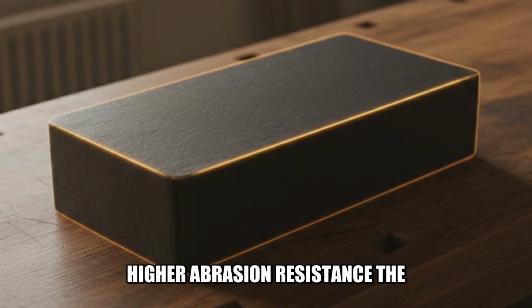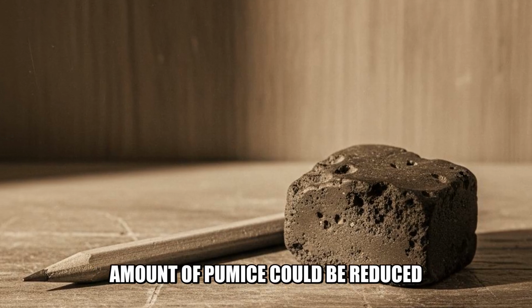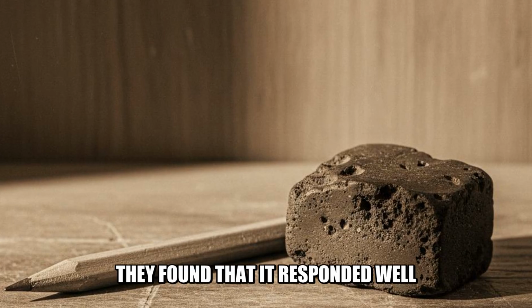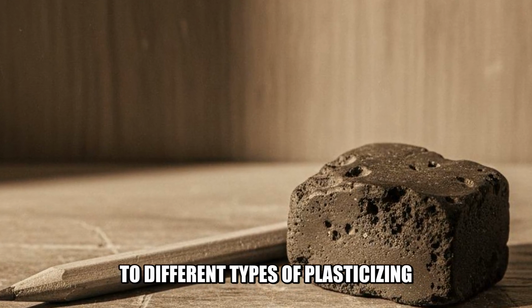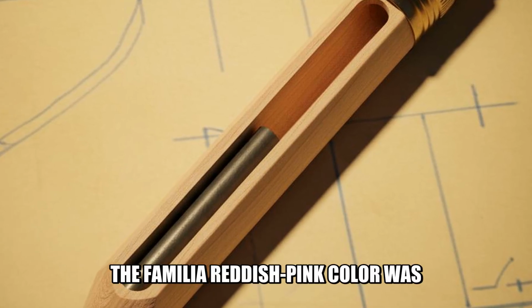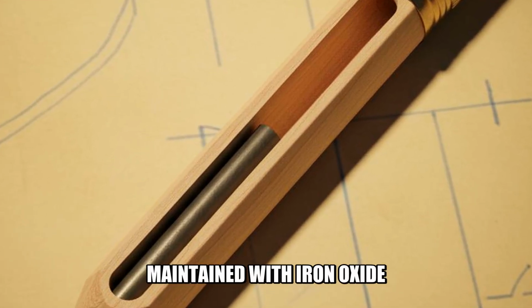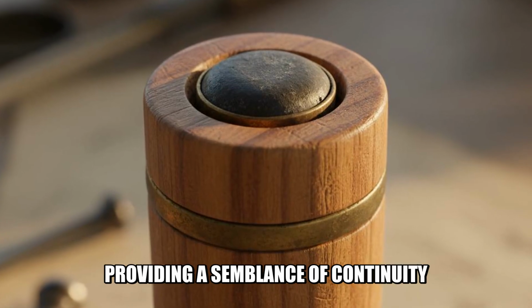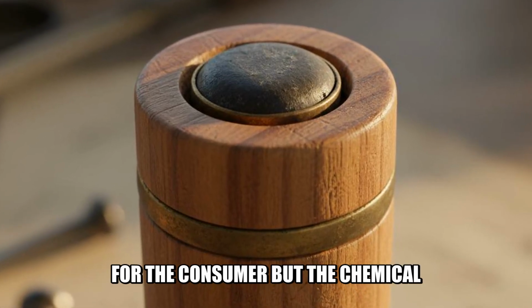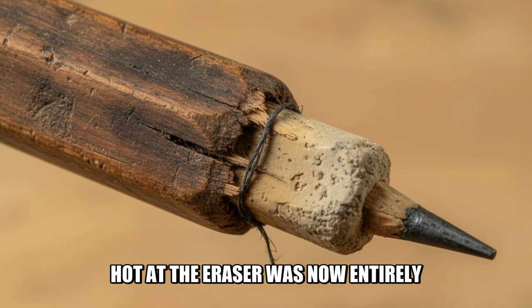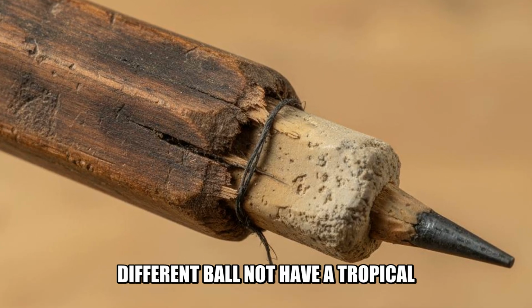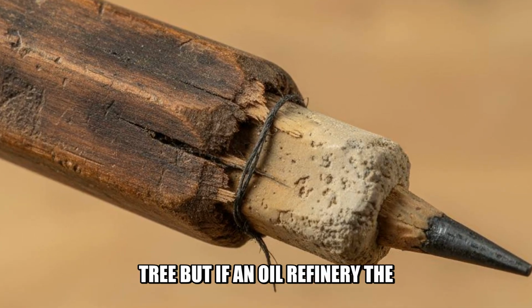They discovered that SBR had a higher abrasion resistance than natural rubber, which meant that the amount of pumice could be reduced. They found that it responded well to different types of plasticizing oils and fillers. The familiar reddish-pink color was maintained with iron oxide, providing a semblance of continuity for the consumer, but the chemical heart of the eraser was now entirely different, born not of a tropical tree, but of an oil refinery.